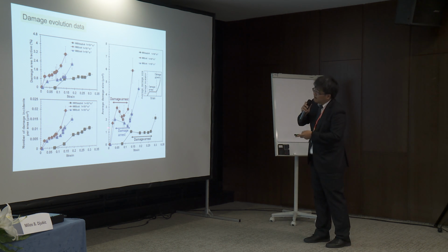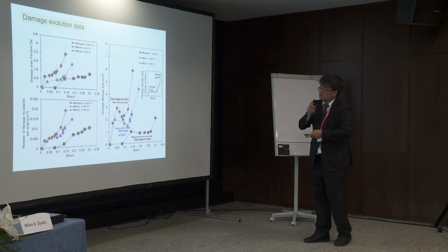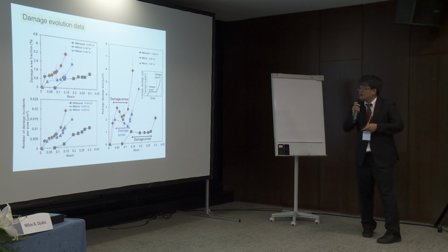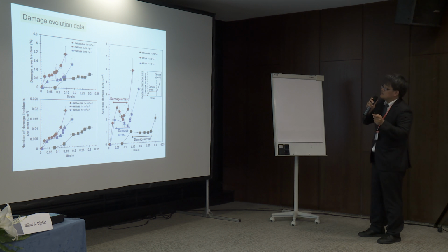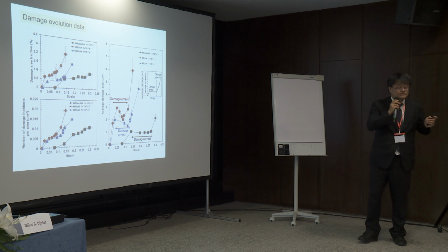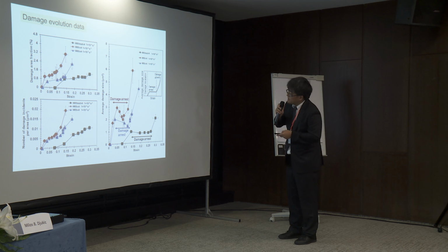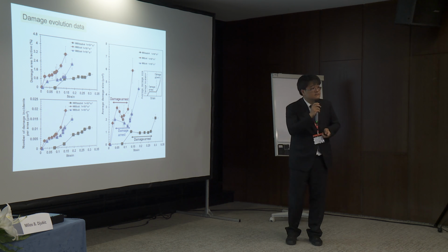Such very small nanoscale nanovoids form everywhere. More specifically, such nanovoids form even just after yielding. In terms of average damage size, just similar to the other multiphase steels, damage is arrested, meaning the size remains constant, then starts to increase, then failure. The point is, even with hydrogen, damage was arrested somewhere.